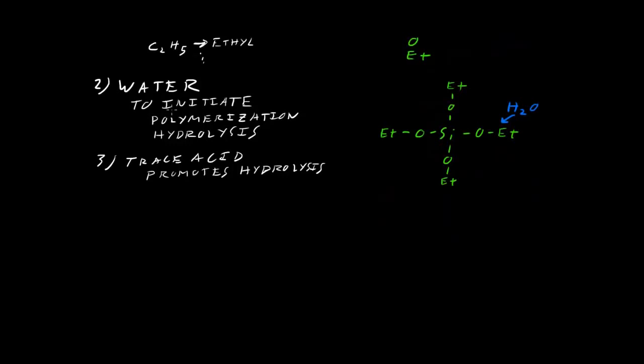The remaining OH from the water bonds with the ethyl that it just kicked off to form ethanol, and that just floats off into the distance. Now this happens on all the other reactant groups, so we have a fully hydrolyzed silane.